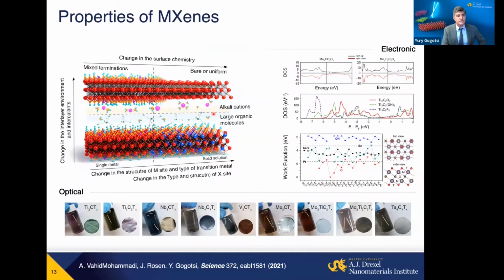But we can move even further. We can graft organic molecules on the surface, for example, without killing electronic conductivity, because the electrons of the transition metal in, say, the inner layer, particularly in thicker structures, will provide electronic conductivity. In assembled multi-layer structures, we can intercalate ions to further change the properties.